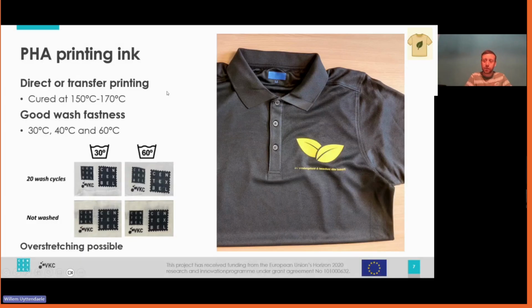A second development we have done with these PHA type plastisols is use them as a printing ink, more specifically in screen printing. Screen printing is a technique quite commonly used in printing clothing. And so with these PHA plastisols, we were able to apply a PHA-based print on top of different types of textiles. And we also have shown that they show good wash fastness at 30, 40, and even 60 degrees.